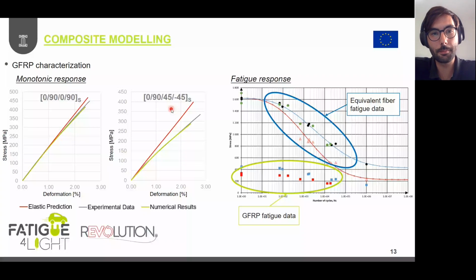Once we characterize the matrix and the resin, the serial parallel rule of mixture is able to compose the behavior of each material with the corresponding rotation, volumetric participation, etc. So there is only one calibration, and then all the layers and combinations are automatically accounted. And now lately, especially with our very good PhD candidates, we have been working in generalizing the fatigue modeling or